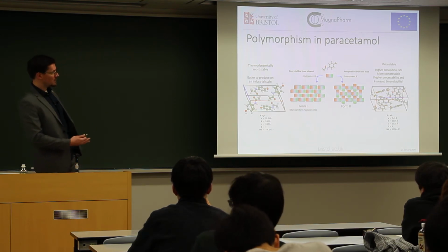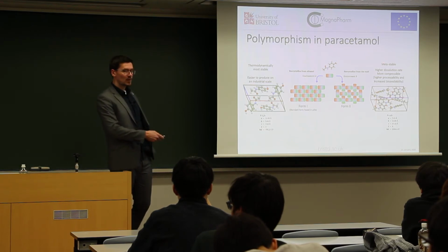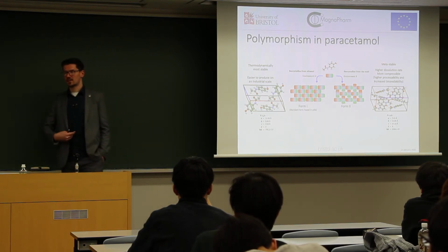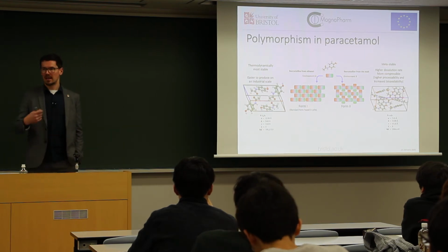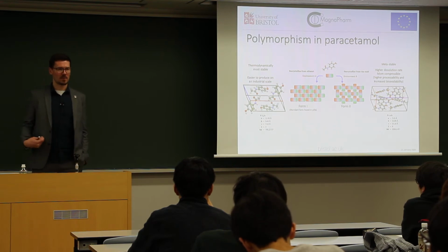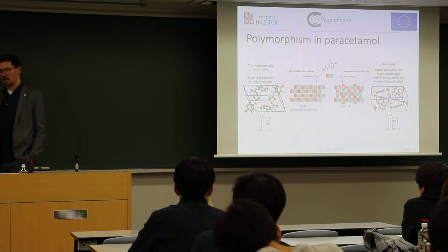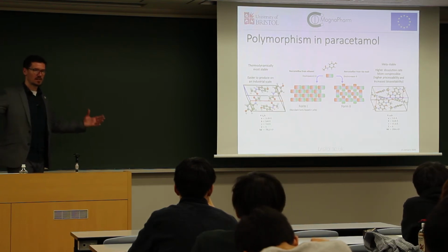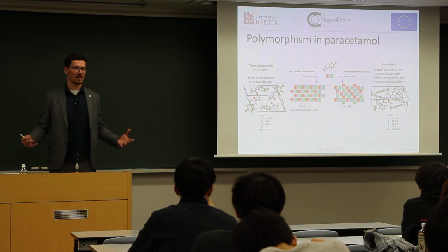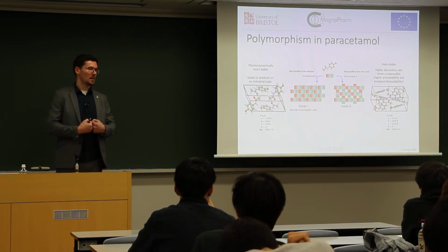However, it does seem to be fairly stable at room temperature, and the reason this is interesting is it's got a higher dissolution rate, which means when it gets to your stomach and hits aqueous acids and water, it dissolves faster and gets into your bloodstream faster, so it's more efficacious. It works better as a painkiller. And it's also more compressible, which means if you're making this on a ton scale, tons and tons at the same time, it's easy to process and press into pellets.